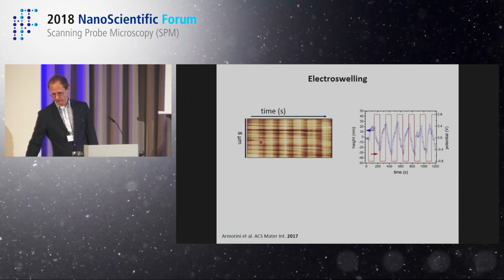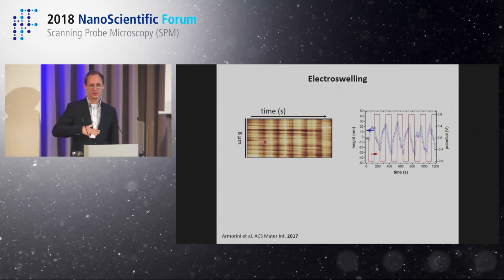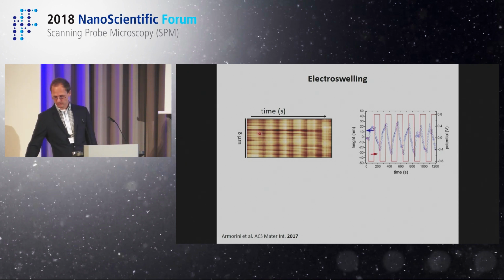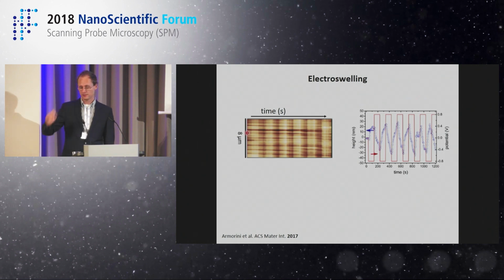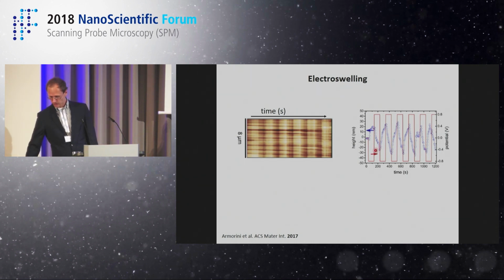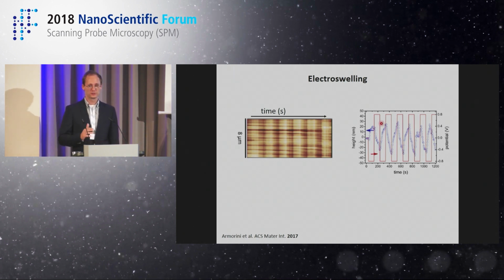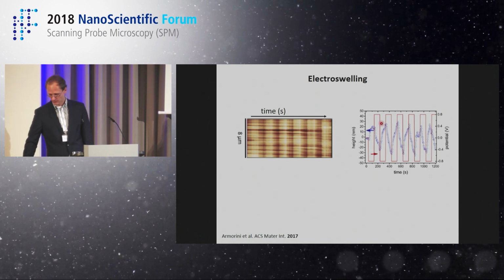You can see that here I have basically a variation in surface height. I do not have a variation in morphology, so these stripes here, they just remain there. It's just that their height kind of changes. This is the plot, so you see that these changes amount even to values of 100 nanometers. So it's kind of an actuating system controlled externally by the potential that I apply.